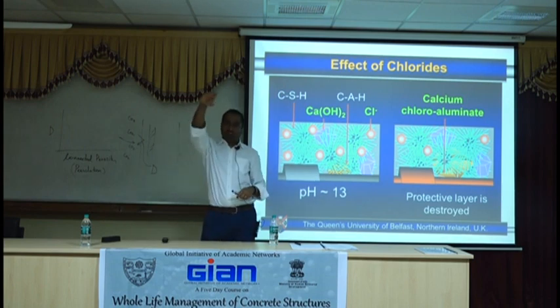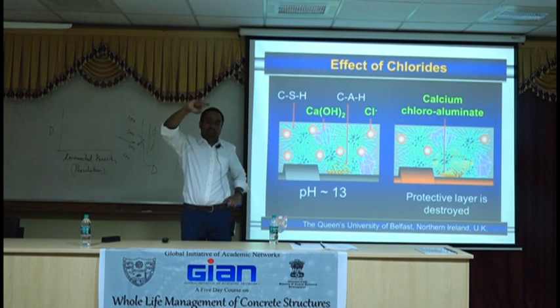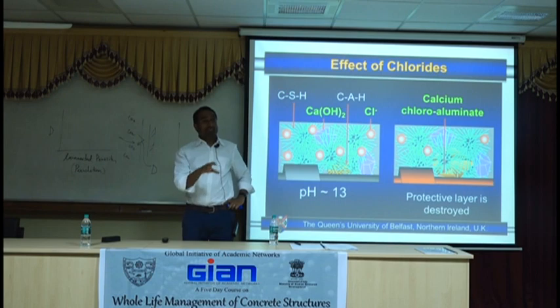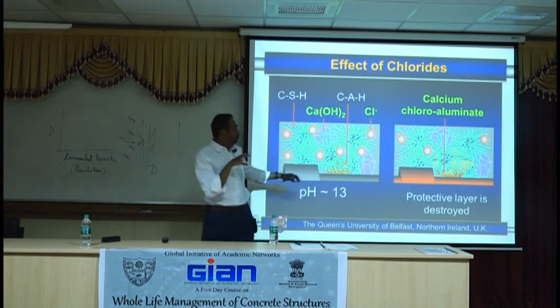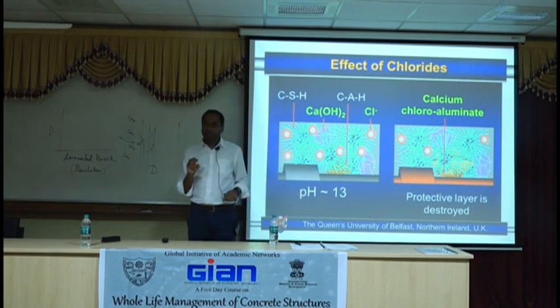Which is where they would list calcium oxide, silicon oxide, aluminum oxide, oxides after oxides after oxides. That table is very important. Fly ash typically has maybe about 12 to 24 or 28% aluminates. I don't know what you get here, but we get something close to 21 percent aluminates in the fly ash. So including more fly ash means you put more aluminates in here.